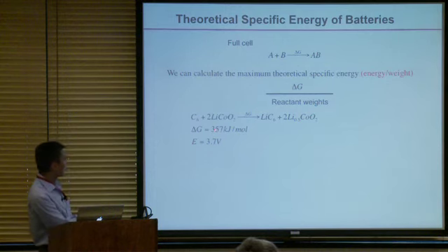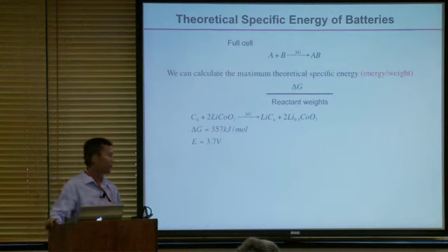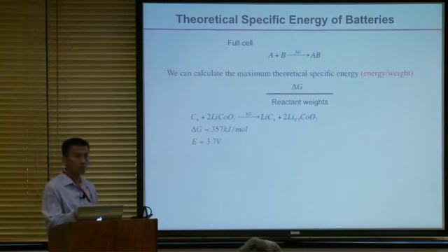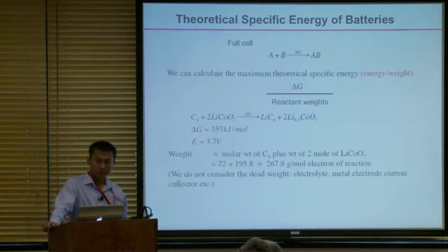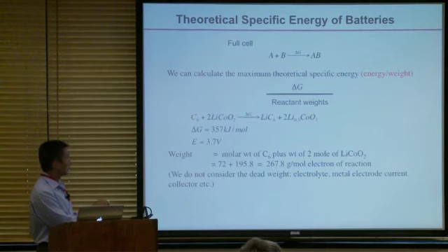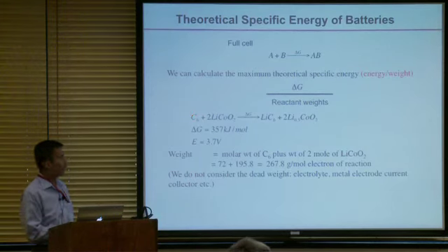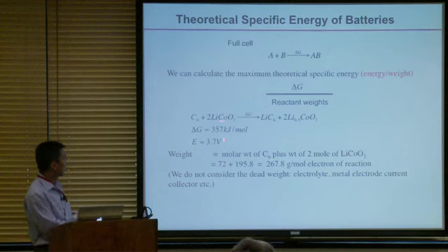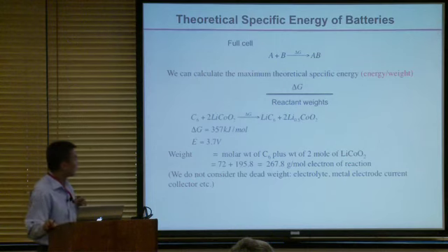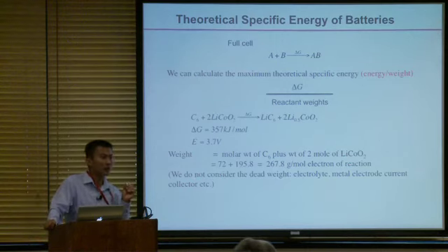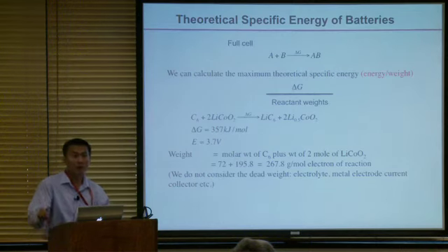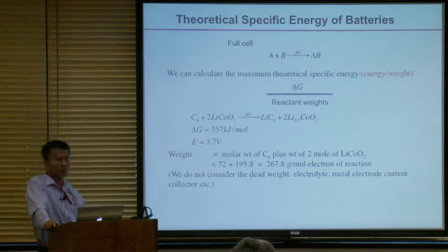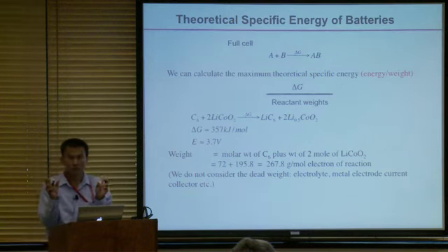Now this free energy change is 357 kilojoules per mole. And you calculate it, the voltage will be 3.7 volts. And now you look at the weight of A and B, these materials, the weight added together per reaction. You have 1 mole of C6, 2 moles of lithium cobalt oxide. You calculate it. This is the weight you put in. So we don't consider other dead weight: electrolyte, metal current collector, etc. This is for calculating the theoretical limit you can get. Every time people talk about a theoretical limit of energy density or specific energy, they refer to only the electrode materials right there, no other dead component.